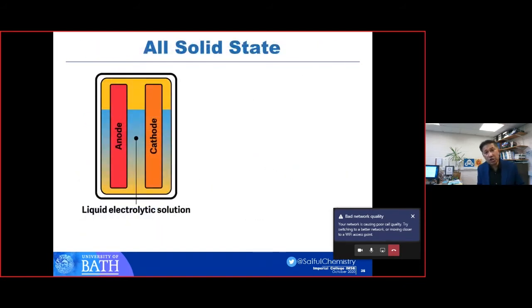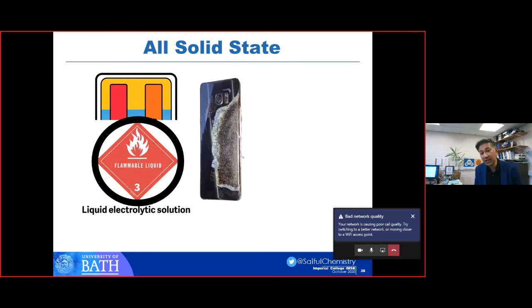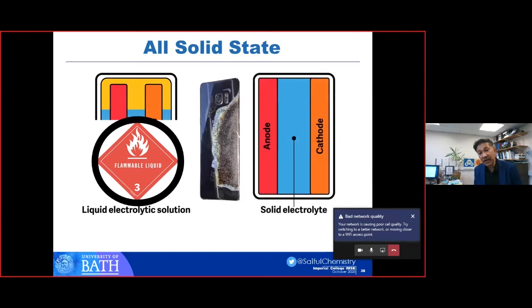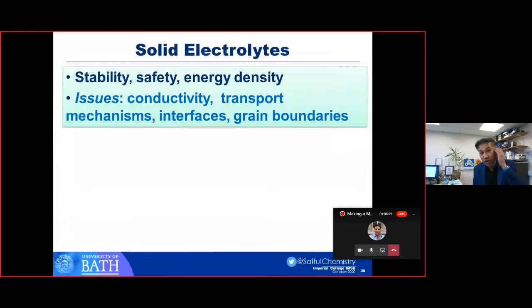Another project that's new is all solid state. The current battery in your phone right now has a liquid electrolyte between the electrodes. And this is a very rare event, but it does happen. A very rare event is that that liquid is flammable, so you can get some thermal runaway. So can you mitigate that? Well, one way of mitigating that is replacing the liquid by a solid, an all solid state battery. And that relies on a solid electrolyte. And the reason why that's much looked at, it increases the stability, the safety, and if you use lithium metal, it can increase the energy density.